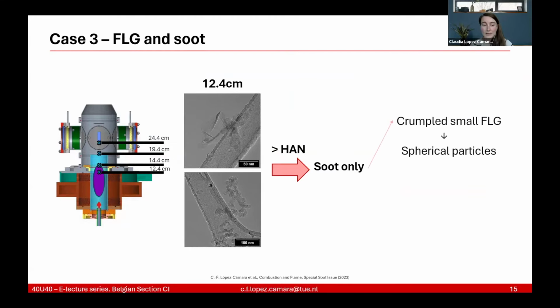The first one is because the few layer graphene crumbles so much that it becomes very small, and they look like spherical particles, but they might not be spherical particles, or they might not be soot, but they might be graphene, but it's really extremely hard to see the difference. And the other option is that there are so many more soot nanoparticles than few layer graphene that when we check on different regions of the sample under the electron microscope, we were not lucky and we didn't find graphene. So these could be two things that are happening at the same time.